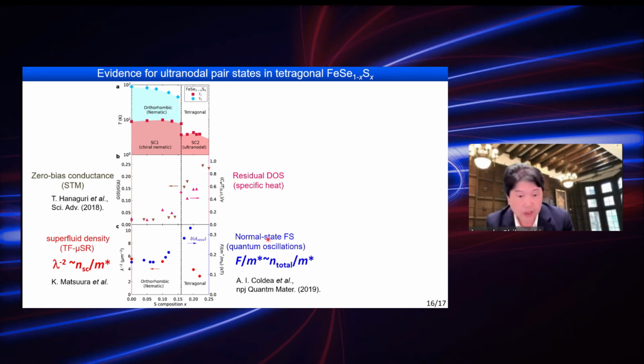So we have used quantum oscillation measurements, and we want to look at the total carrier number divided by m star, which is estimated from the quantum oscillation frequency f, proportional to the Fermi surface volume in the case of quasi-two-dimensional material, divided by m star, estimated from the temperature dependence of the quantum oscillation. This f over m star is plotted by these blue dots as a function of x.